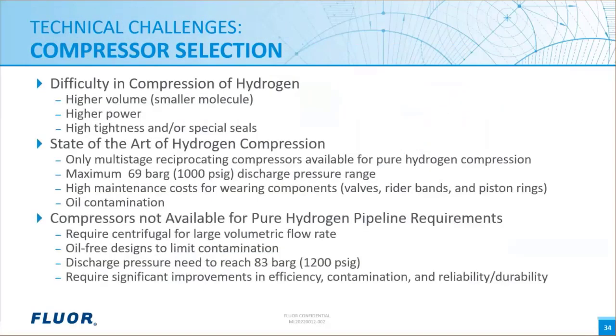Another major technical challenge is the compressor selection. We know that hydrogen volume is 3 times that of natural gas at the same pressure. Hydrogen is very difficult to compress. It has a very small molecule, which has high potential of leakage through containment. The compression of hydrogen requires much more power, higher tightness, and special seals to reach the pressure required for high volume transmission. We know from compressor manufacturers that multi-stage reciprocating compressors are ready for producing discharge pressure up to 69 bar for hydrogen. This is considered the most state-of-the-art equipment for compressing hydrogen.